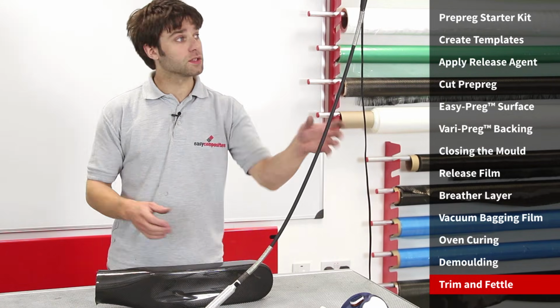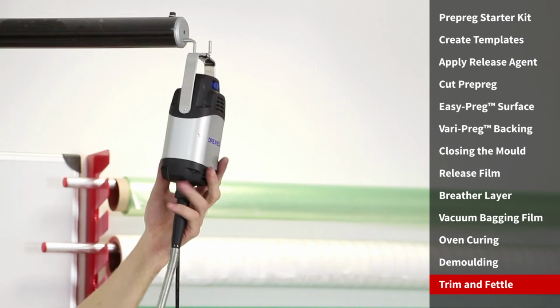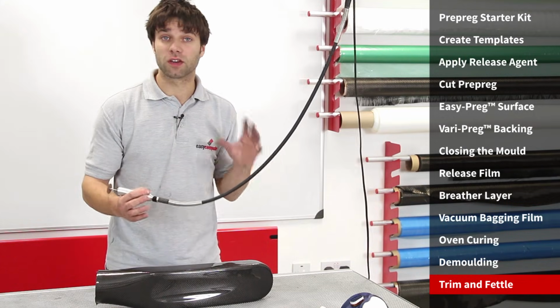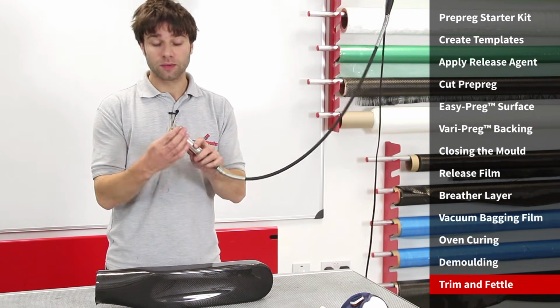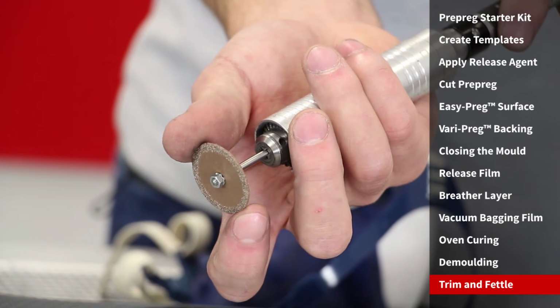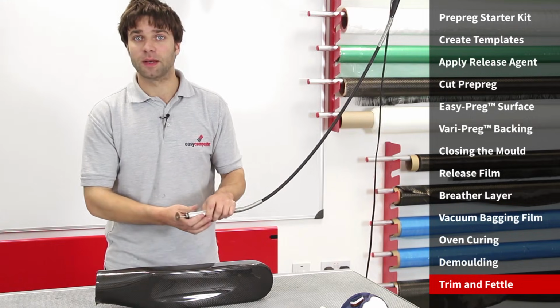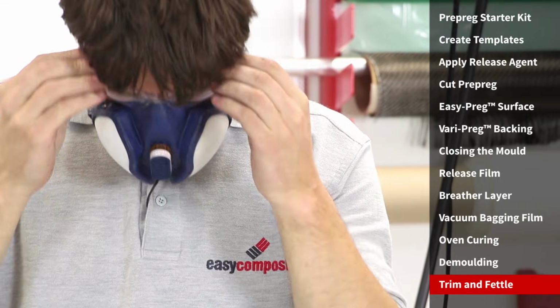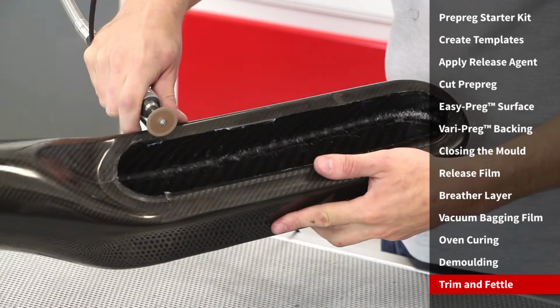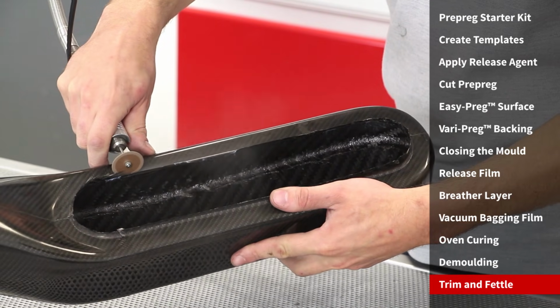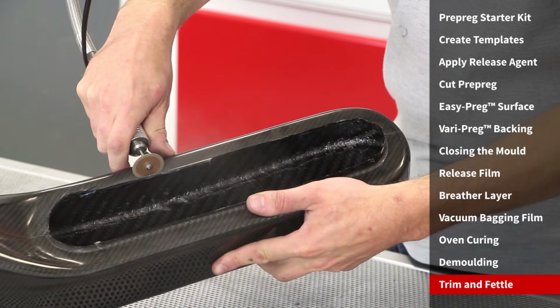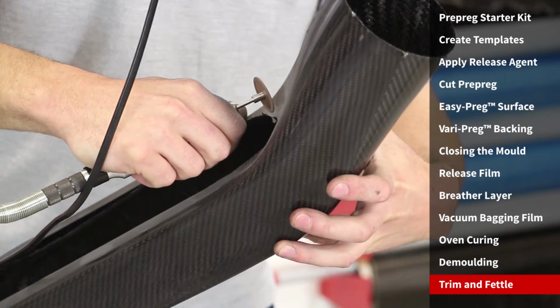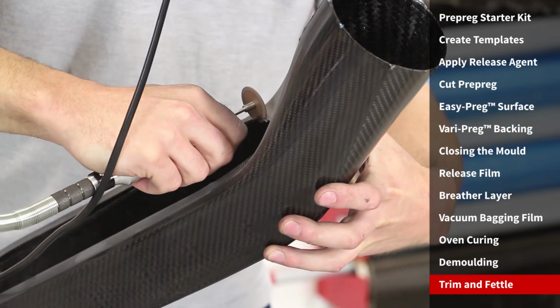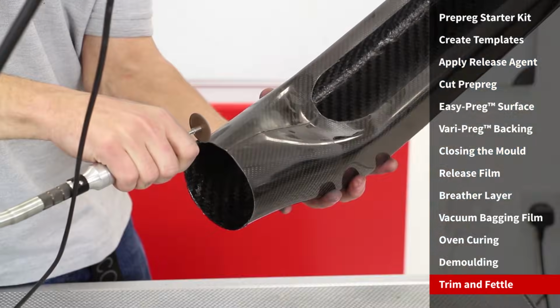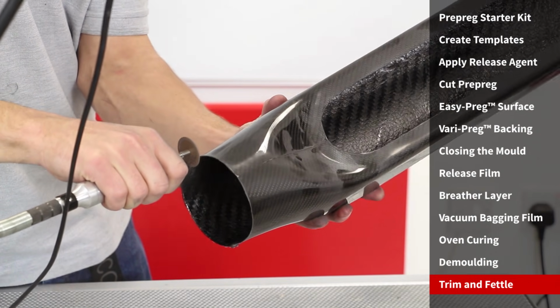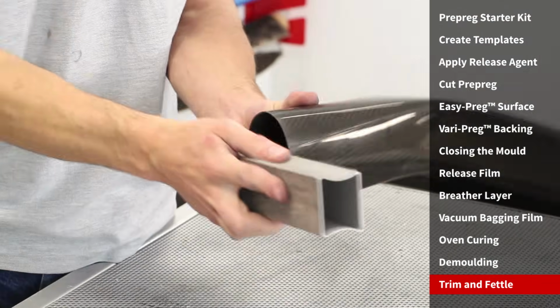To trim the part, we'll be using a Dremel Fortiflex, which in our daily production environment has proven itself to be incredibly reliable. Fitted into the Dremel is a Permagrit tungsten carbide wheel, which is absolutely perfect for cutting carbon fibre. The Fortiflex is great because its remote motor keeps the electrical part of the tool away from the conductive carbon fibre dust, which would quickly damage the smaller handheld models. And its foot pedal operation leaves hands free to concentrate on the trim.